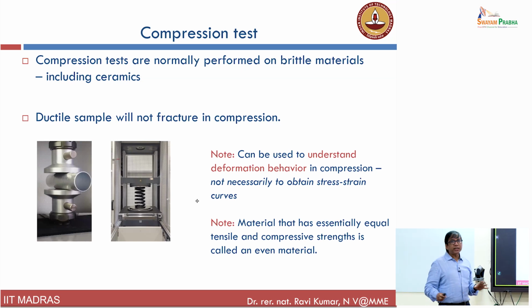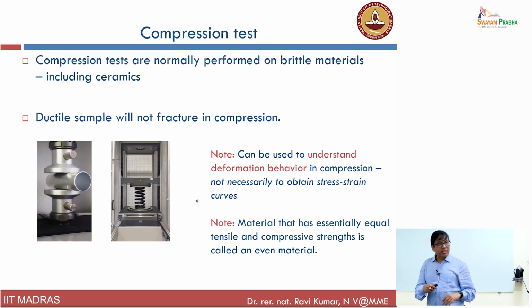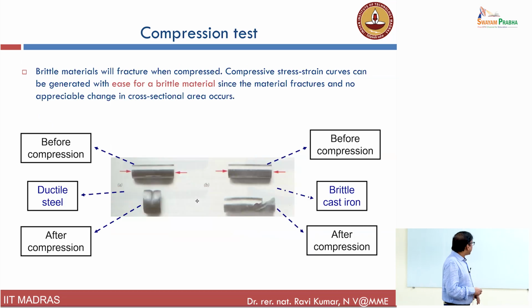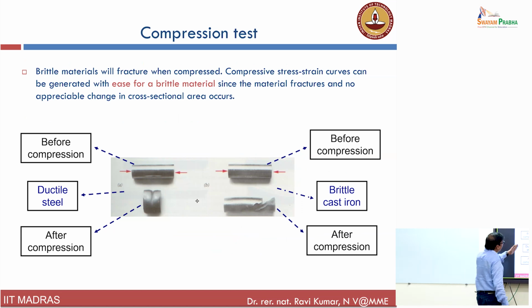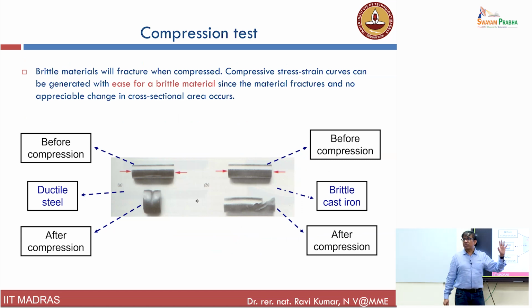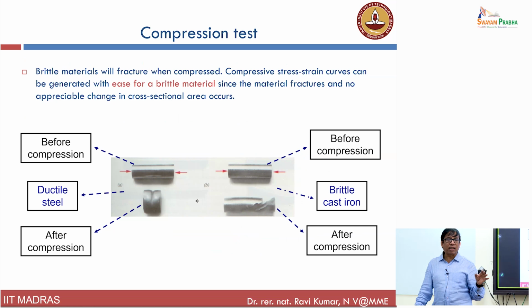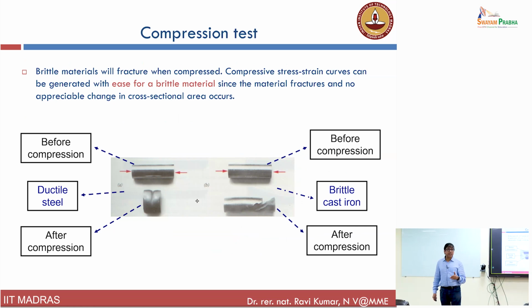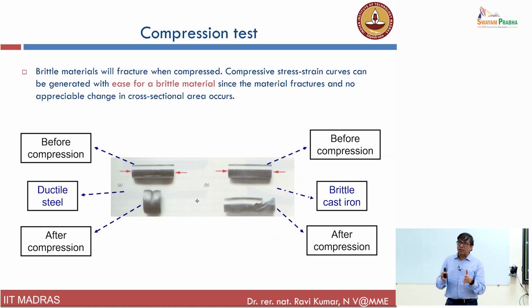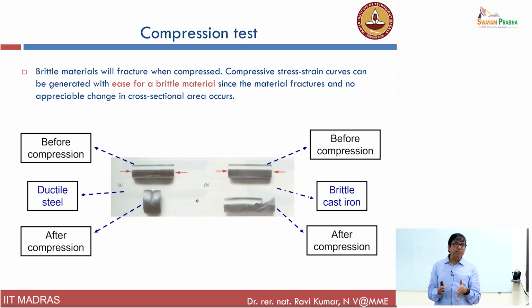And again, look at the application, then decide the testing technique to generate the data. So this is just to give you an example. You never do a compression test for ductile samples, because if you do a compression test for a ductile sample, it typically tends to barrel, and you don't get useful data. On the other hand, if you do a compression test for a highly brittle material such as ceramics, typically it fails in shear at 45 degrees.